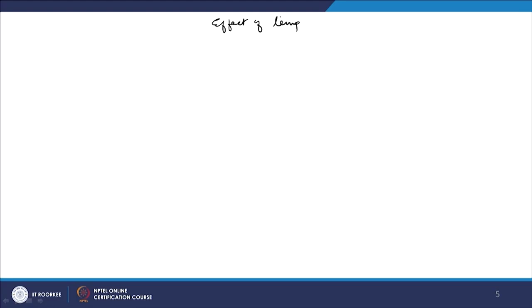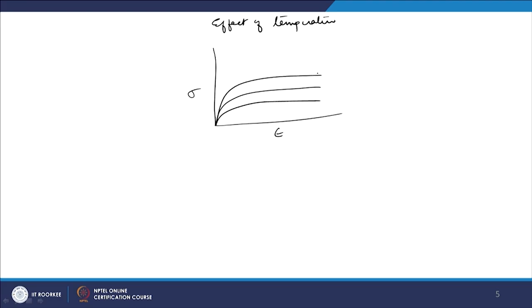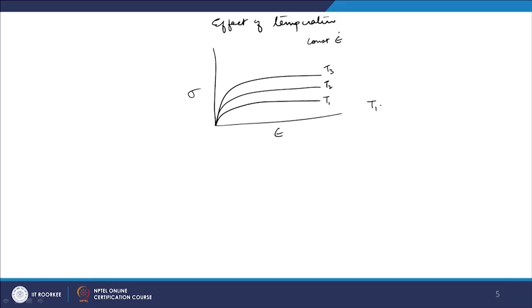Now, what will be the effect of temperature? Again I am drawing some flow stresses here, sigma versus epsilon. I am taking a simplified steady state type of flow, and giving them some temperatures T1, T2, T3, and these are all done at constant strain rate. When you want to change temperature, you have to fix the strain rate as constant and keep changing the temperature for different samples, or you can do it at a constant temperature and keep changing the strain rate for different samples. From the flow stress value, I can tell you that my T1 will be more than T2, and it will be more than T3.